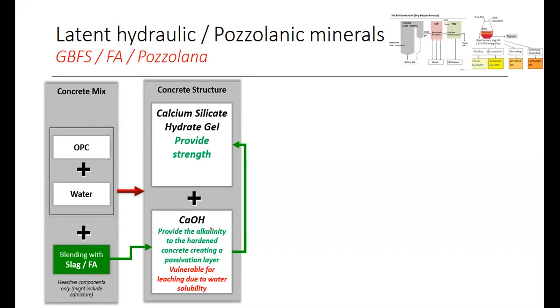So by improving the alkalinity of that particular mixture, we can dissolve those aluminosilicates to get the required calcium and aluminates into the solution. After that, those can react with the calcium hydroxide to form a similar product, which is calcium silicate hydrate gel, which provides additional strength. And similarly, that could reduce the existing porosity, which is good.